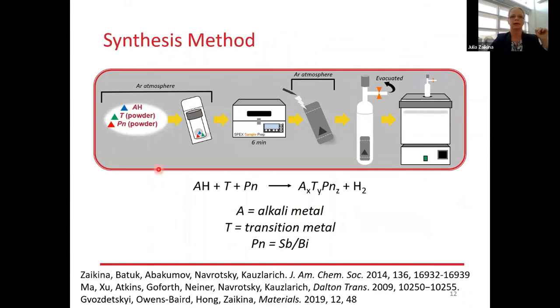We mix our alkali metal hydride precursor with transition metal and metalloid, either antimonide or bismuthide. We then mix them well, and then load the mixture into the niobium or tantalum tube, because similarly to elemental alkali metals, hydrides are very reactive and they would attack silica. So once this niobium tube is sealed, we put it into the specially designed silica reactor, which goes then into the high temperature furnace, which can be programmed.